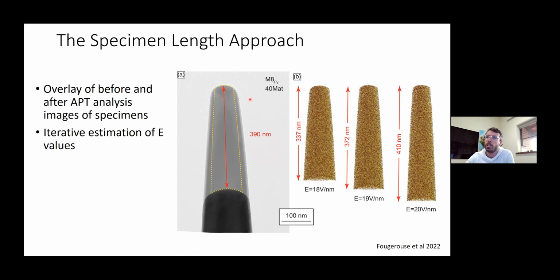I must say that in order to have a nice tip shape to start with, we have first put the specimen in the atom probe and run them for a few million atoms to make sure that we have a stable evaporation and hemispherical tip shape, and then we can do our accurate imaging and do that exercise. Following the analysis, we can reconstruct the data. Then we can iteratively test some field values and see what works and gives us some good results. Some sort of a coarse approach to start with, and then we can later refine.